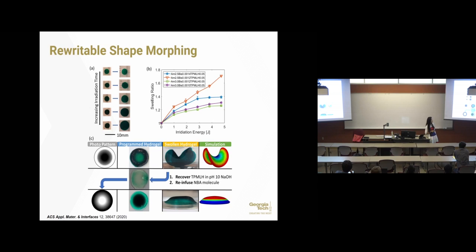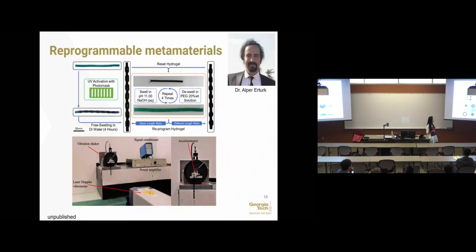And because in this reaction we take away the product, we can also give it back. Put it in a high pH solution, and it will recover. Then we can come in with a different pattern, so it's reversible. Here we use an inverse pattern of the previous one as a demonstration. You have more light penetrating through in the middle and less in the outer region, so it becomes an inverse dome shape this time. This is just to demonstrate some capability.